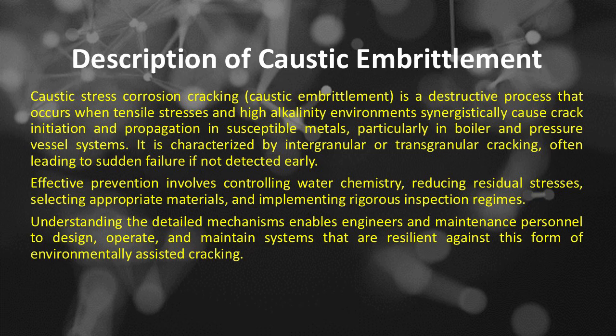Caustic stress corrosion cracking, caustic embrittlement, is a destructive process that occurs when tensile stresses and high alkalinity environments synergistically cause crack initiation and propagation in susceptible metals, particularly in boiler and pressure vessel systems. It is characterized by intergranular or transgranular cracking, often leading to sudden failure if not detected early. Effective prevention involves controlling water chemistry, reducing residual stresses, selecting appropriate materials, and implementing rigorous inspection regimes. Understanding the detailed mechanisms enables engineers and maintenance personnel to design, operate, and maintain systems that are resilient against this form of environmentally assisted cracking.